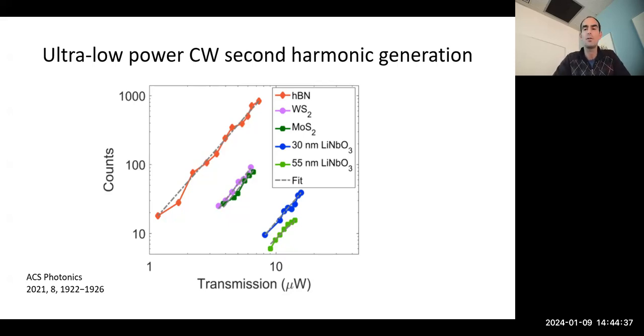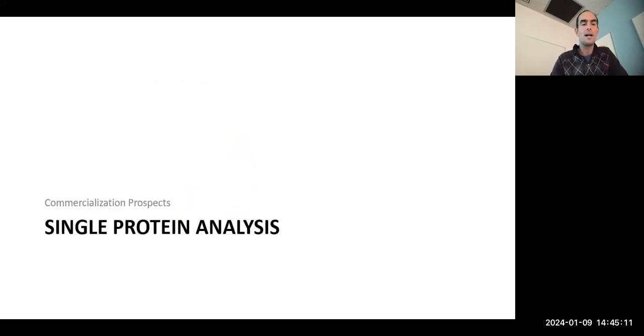Lithium niobate is one of the most popular nonlinear materials. It has a large second order susceptibility, so it's a good nonlinear material. Our collaborators at Simon Fraser University, Byron Gates, provided us with some lithium niobate nanocrystal samples they had made. Compared to those nanocrystals, these two-dimensional materials have orders of magnitude more second harmonic generation, even though they're just a single layer. So that was quite surprising and interesting to us.